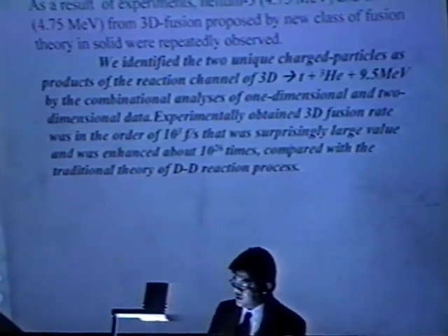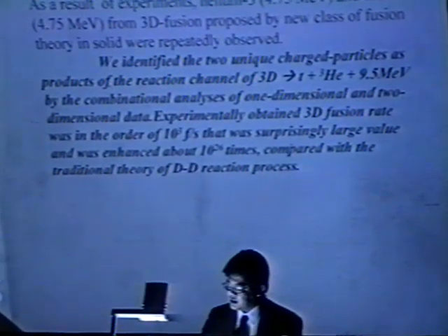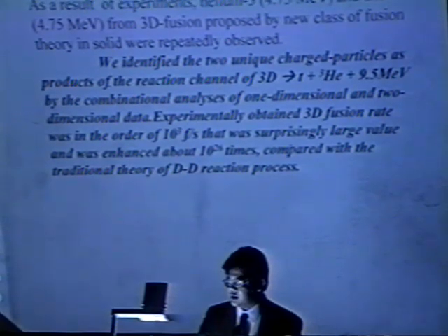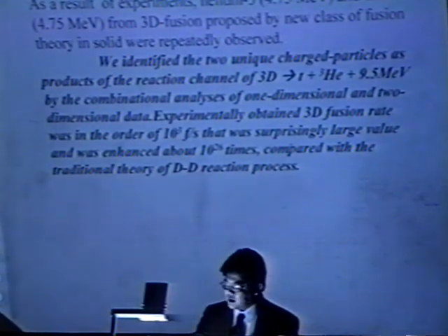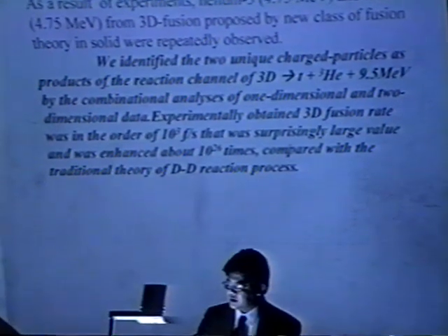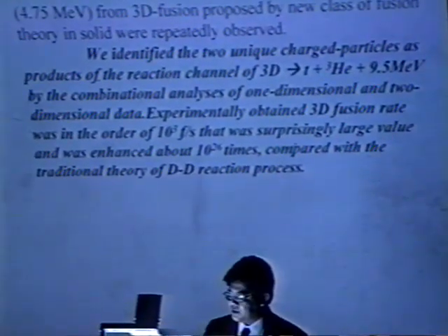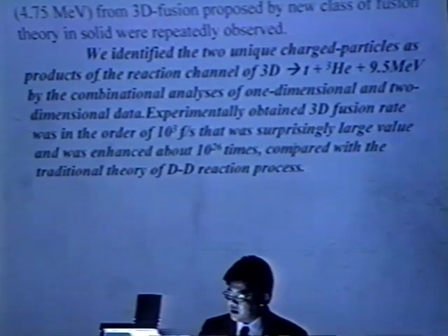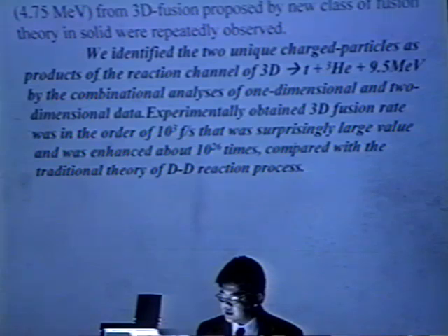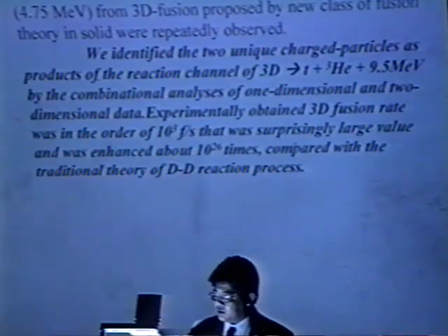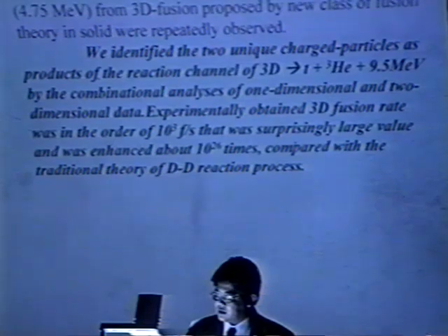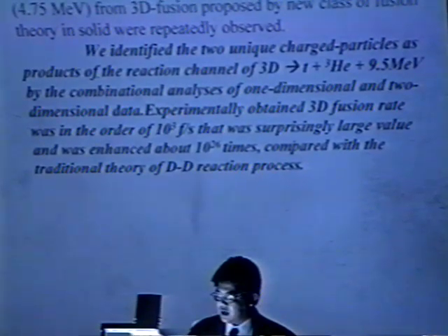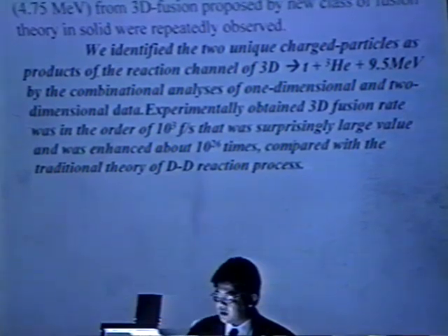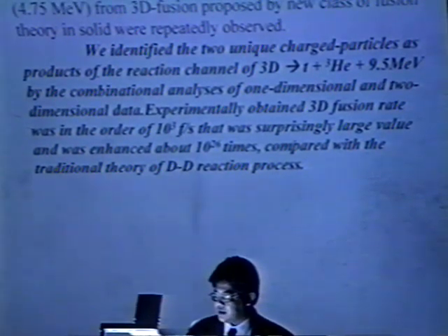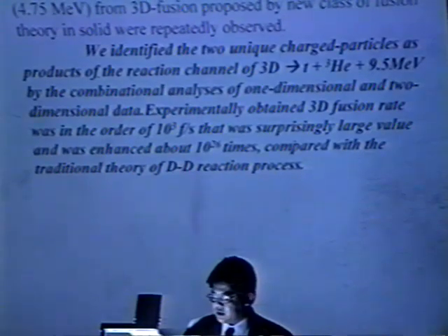We identified two unique charged particles as products of the reaction channel of 3D. By the combinational analysis of the one-dimensional and two-dimensional data, the experimentally obtained 3D fusion rate was on the order of 10 to the 3, which was a surprisingly large value and was enhanced about 10 to the 26 times compared with the traditional theory of DD reaction.